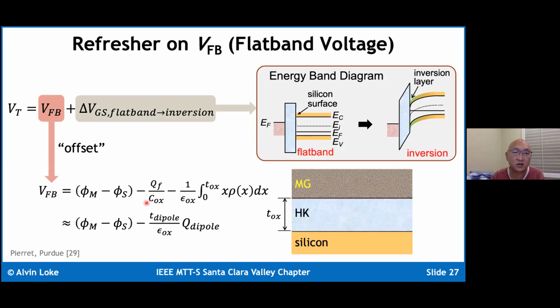It consists of a host of different terms. Most notably, it consists of a work function difference between the gate and the silicon surface side. Also fixed oxide charge at the silicon dioxide surface interface, which is becoming increasingly insignificant because increasing COX makes this term less relevant. But then you also have fixed charge in the dielectric that can also shift the VT. You can adjust the flat band voltage by adjusting the work function of the gate metal, but you can also induce dipoles into the HighK dielectric in order to adjust the VT as well. And the depth of this dipole and the charge density of the dipole can dictate how much you can adjust the threshold voltage. Okay.